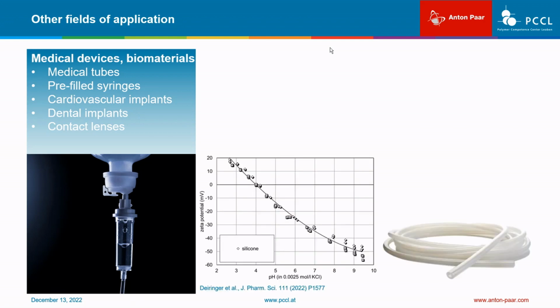As an example, let us look at the surface inside a silicone hose for the transportation of antibody formulations. The Zeta potential represents a significant interfacial charge that is negative above the isoelectric point at pH 4, which is a typical property of a pristine polymer-water interface. Note that despite the complex geometry of a flexible tubing, we find a remarkable reproducibility of the Zeta potential.